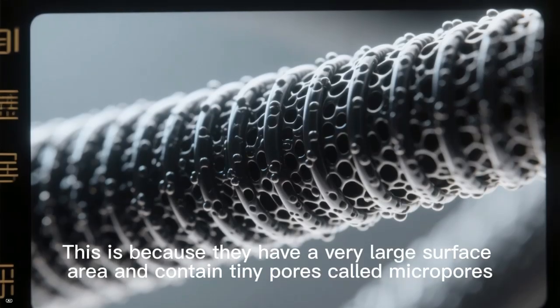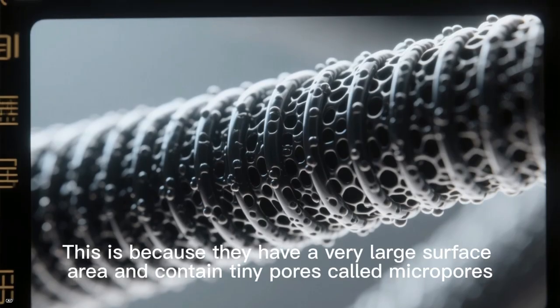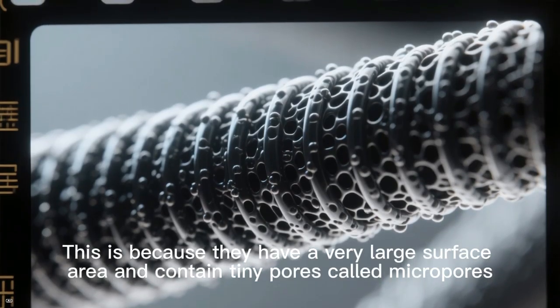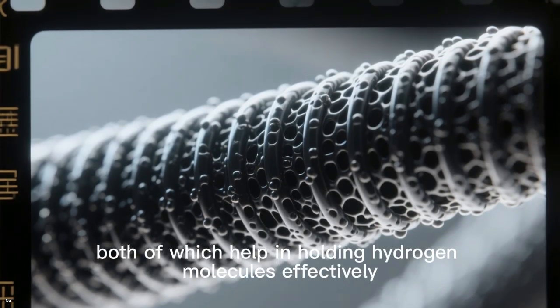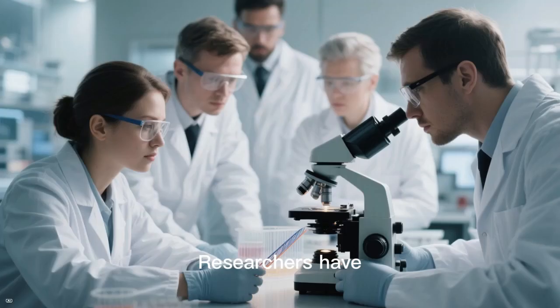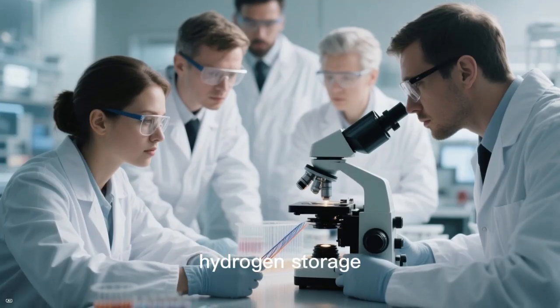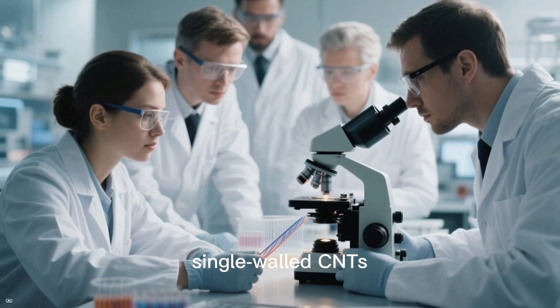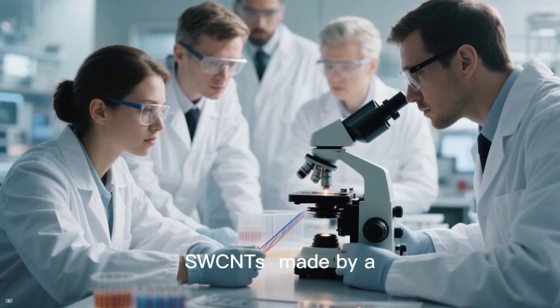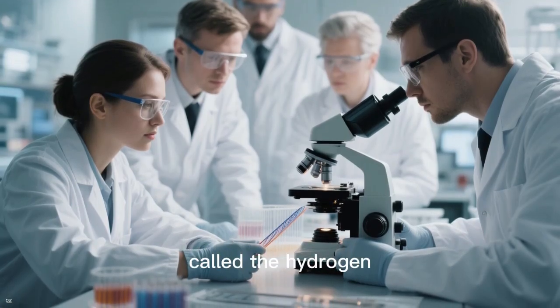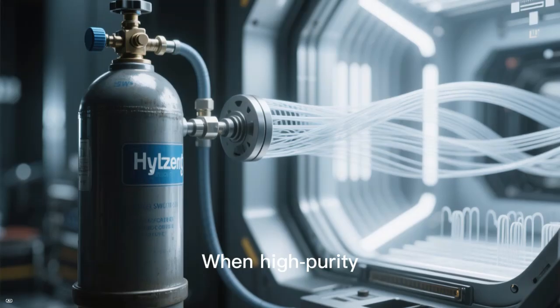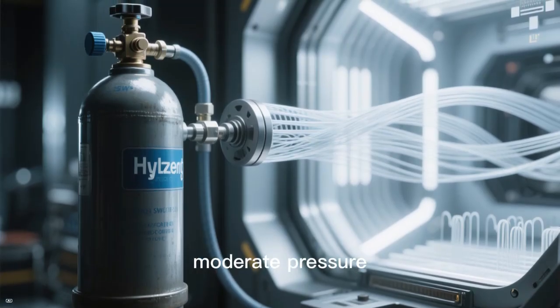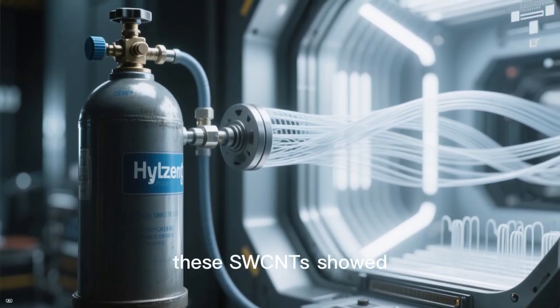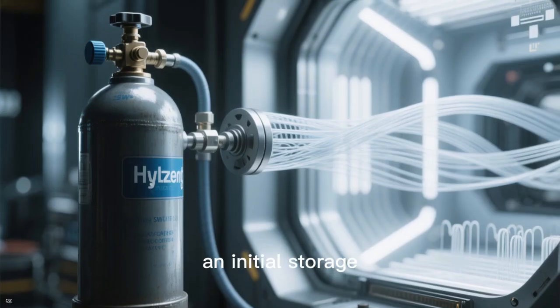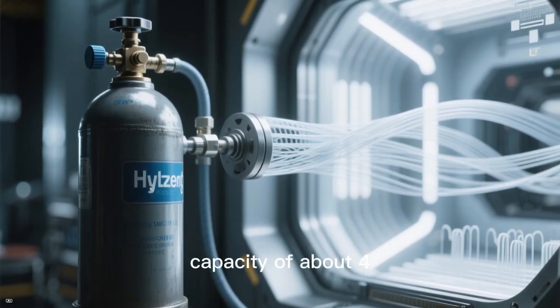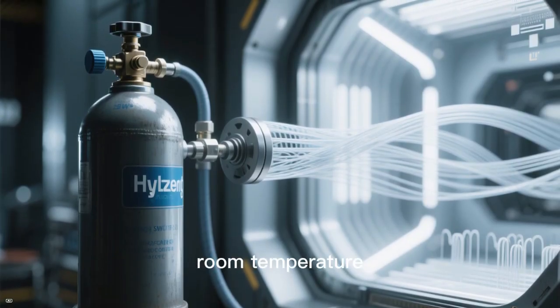This is because they have a very large surface area and contain tiny pores called micropores, both of which help in holding hydrogen molecules effectively. Researchers have studied the hydrogen storage capacity of single-walled CNTs, or SWCNTs, made by a special method called the hydrogen arc technique. When high-purity hydrogen gas at moderate pressure was introduced, these SWCNTs showed an initial storage capacity of about 4.2% by weight at room temperature.